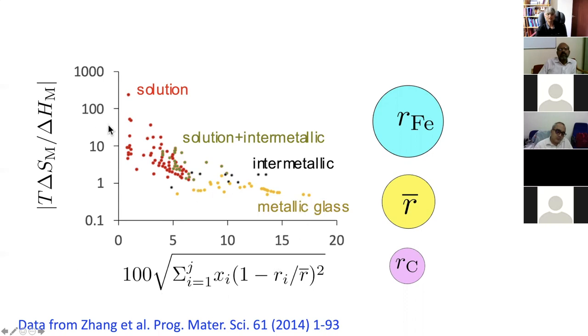And these data show you solutions tend to occur when the misfit is small and when the contribution from the entropy of mixing is overwhelming. Okay. So this can be taken as a general rule when you're thinking of designing your high entropy alloys, that you want the enthalpy of mixing to be small and you want the atomic misfit also to be small.